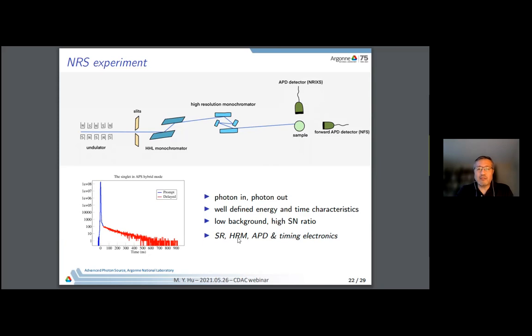The monochromator and the APD timing are important, but also the timing structure, because this is what the detector sees. For example, the APS particular mode is this hybrid mode. So you have this prompt, we call it prompt, coming in every 3.6 microseconds in that mode. Everything else pretty much decays fast, because all the electronic processes are fast. They die out. But the nuclear response is still decaying, with a longer lifetime on this scale. So you see, these are our signals.